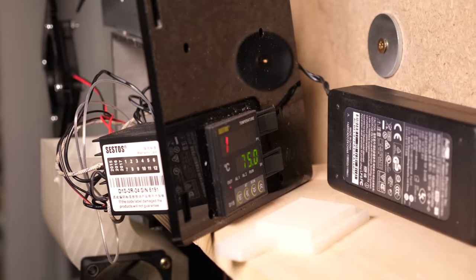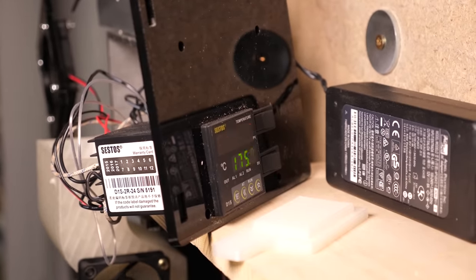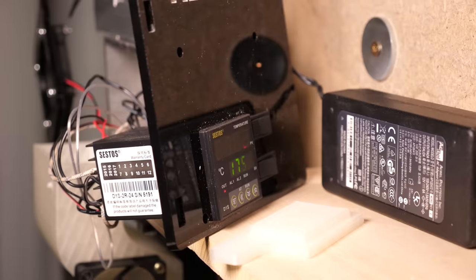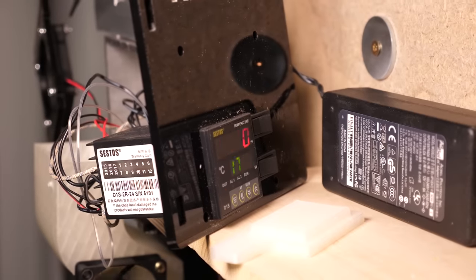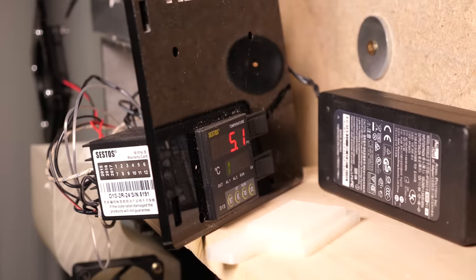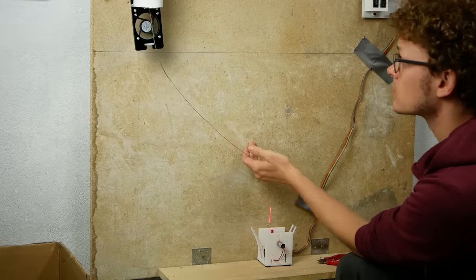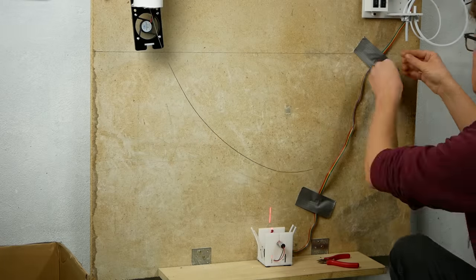After bumping the temperature up all the way to 175°C the material extrudes very smoothly but due to the low viscosity of the melt ends up way undersized so I drilled the nozzle to 2.1mm. Anyways, so the shredded and dried PLA scraps are now added to the hopper. After a bit of filament starts to extrude it is slowly guided through the position sensor to the winder.